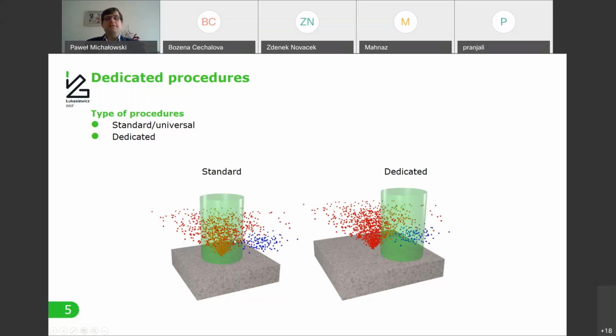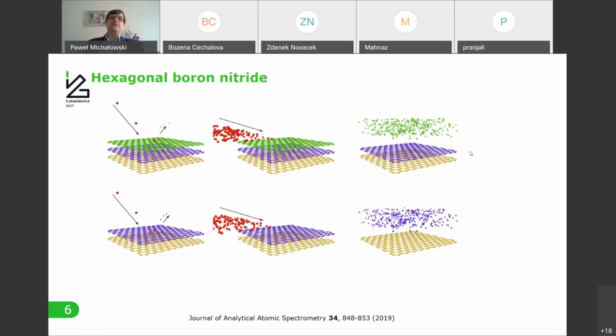So in my work, I spent a lot of time to create the dedicated procedures. So I don't optimize the total number of ions which are detected, but optimize these ions which are the most interesting ones. So in here, as I mark here, this procedure is optimized in such a way to detect the blue types of atoms. And more importantly, I can also change the extraction parameters during the analysis, so I can switch from one type of atom to another whenever I need it. It's making a little bit more complicated analysis, but in this case, I'm gaining a lot of signal intensity. So then I don't need to worry about the noise of these signals, and I can really achieve the sub-nanometer depth resolution.